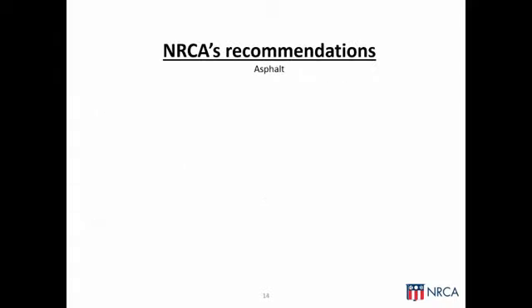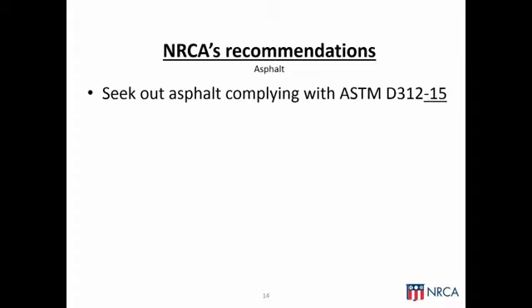So when it comes to asphalt, NRCA has some recommendations. First off, we recommend you seek out asphalt complying with the new edition of the ASTM standard. Not only should we get to a point where we have lower kettle and tanker temperatures, but then also lower EVT temperatures with an adequate spread for proper installation. And that standard is specifically designated as the -15 edition, so that's something you're going to have to look at.